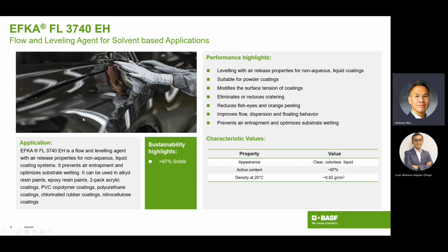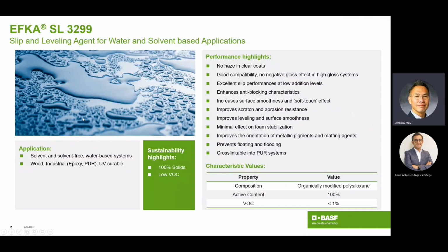3299. EFKA SL 3299 is a slip and leveling agent. So it's similar to the 3740 in that it will help you improve your wetting. It will help you to get good flow or a level profile in your film. But more importantly, it also brings one additional characteristic, and that is surface modification.